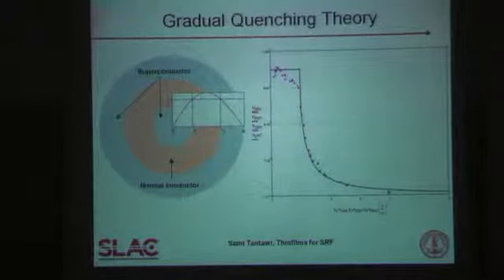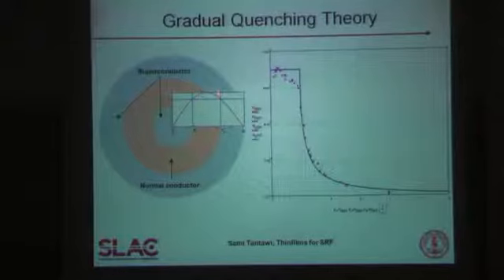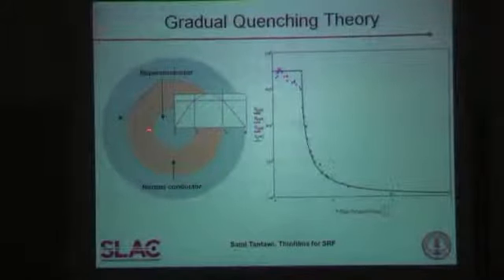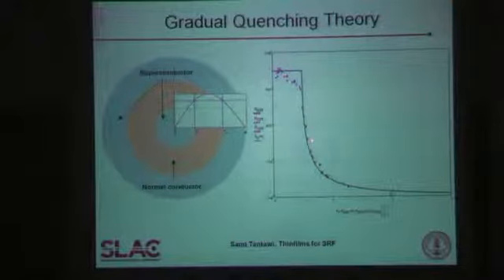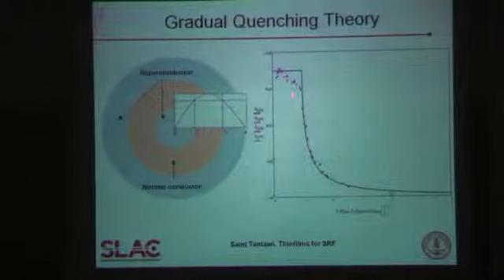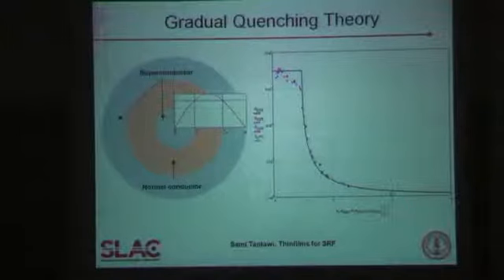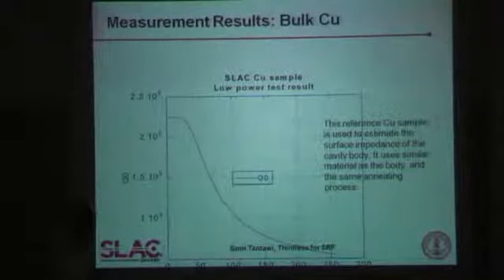This drove us with Joshi's group to write a model for this cavity. We assumed that once you exceed a certain field limit on the sample, the portion of the field inside the cavity in that region will quench while the rest of the cavity stays superconducting. As you increase the power, the quenching area grows gradually. From this model we derived a theoretical curve for the quenching limit that fits very well, except that it fits perfectly only if we assume the sample temperature is about 7 Kelvin rather than 3 to 3.5 Kelvin — which stayed a puzzle for a while.